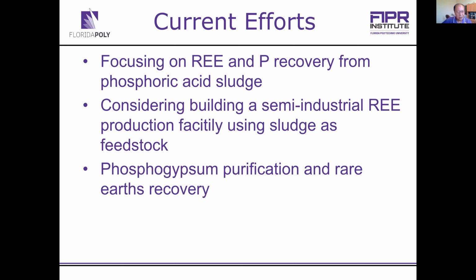Although the rare earth concentration in this sludge is the highest among the phosphate mining process and streams, phosphorus still has much higher value in this sludge than rare earth. So in order to improve the economics, you have to recover the phosphorus as a high value product. Otherwise, it's still very challenging to recover the rare earth elements economically, even though the concentration is much higher than other streams. So we are doing that. We're going to try to get the phosphorus separated from the sludge first, then get the rare earth elements leached and recovered.